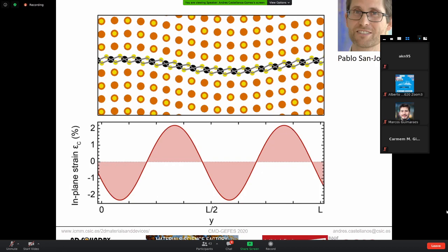and that does reduce their energy, becoming more favorable. Therefore, what this model says is that the most stable solution for the lattice is to have this spatially varying strain profile in plane. So basically, the atoms get expanded, compressed, expanded, compressed, in order to accommodate each other's lattices and become commensurate. We start from a system in which, when we stack the layers, they should be isotropic. And once they start to interact, the atoms start to move around a little bit in order to accommodate the two lattices. And they do that by breaking the symmetry of the system.